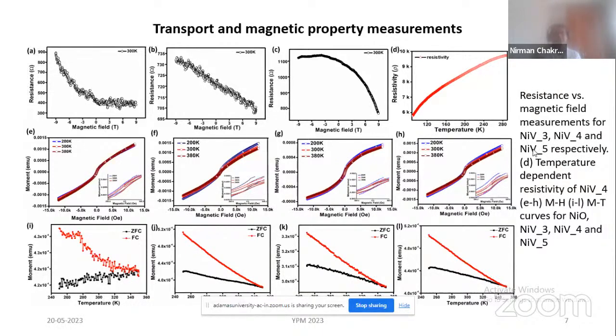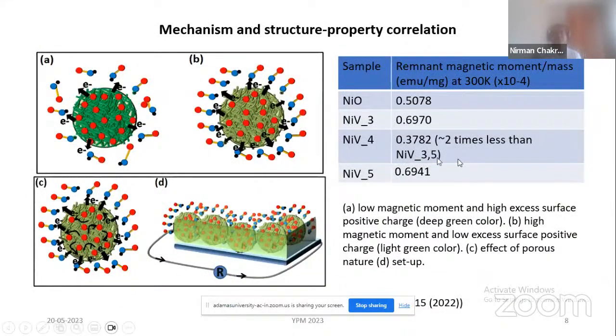And then we performed magnetic measurements of the samples. To our surprise, nickel oxide is typically antiferromagnetic, but when we did the magnetism experiments, we found that our samples are actually soft ferromagnets. Soft in the sense that they have less remnant magnetic moment per unit mass as compared to strong ferromagnets like Fe3O4. If we compare the magnetic moments of our samples, we find that for NiV4, the remnant magnetic moment is least, which is two times less than the two other doped samples.